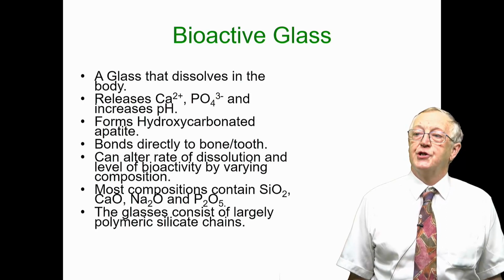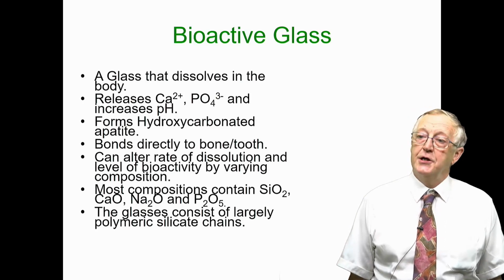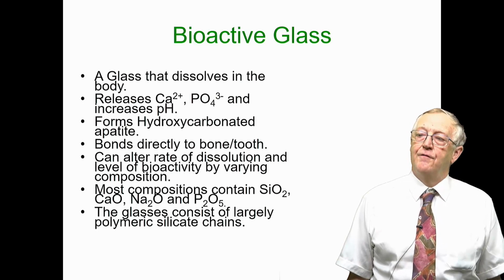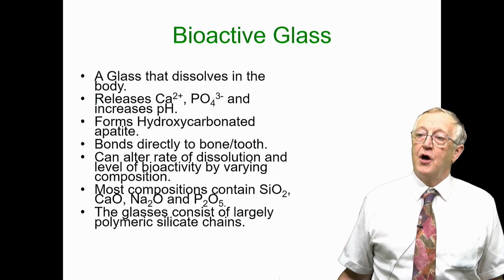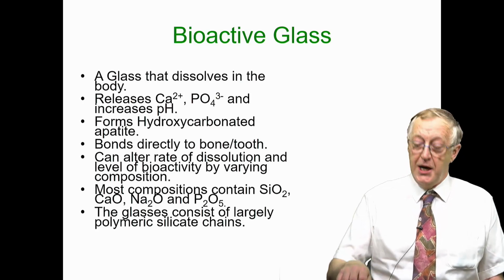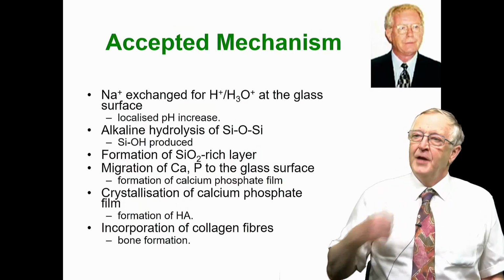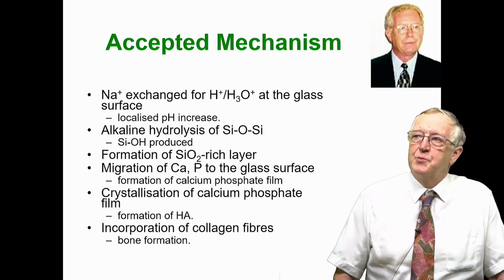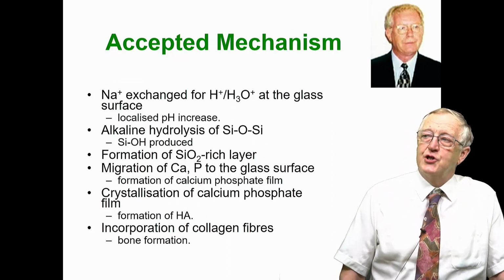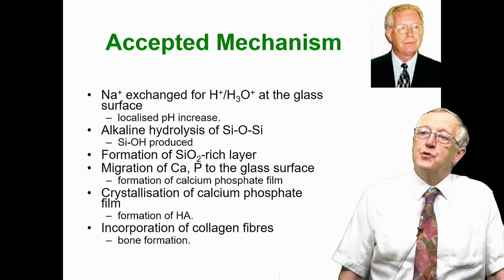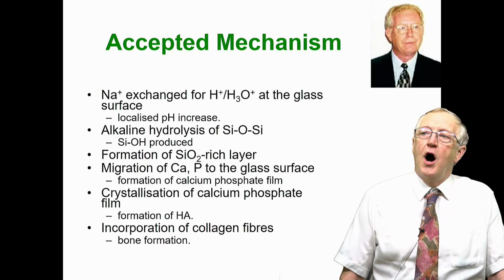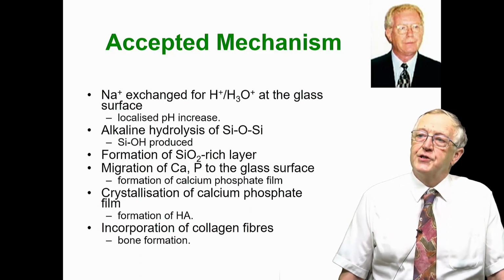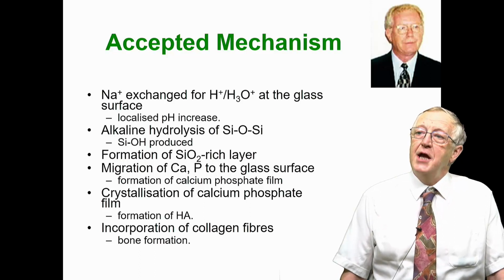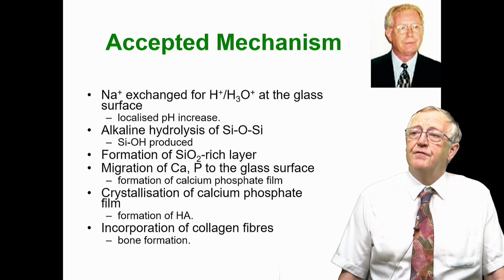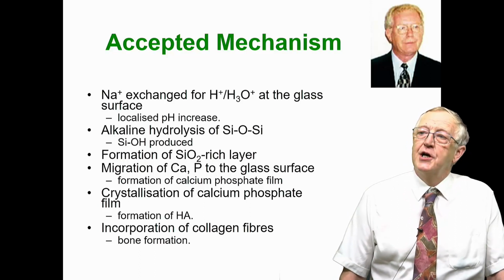And most compositions contain silica, calcium oxide, soda, and phosphate or P2O5. And the glasses consist largely of polymeric silicate chains. The accepted mechanism proposed by the inventor of bioglass, Larry Hench, shown in the top right there, is as follows. Sodium ions are exchanged for hydrogen ions at the glass surface. This exchange results in a localized pH increase, and this is particularly attractive for dental applications because caries and tooth decay occurs under acid conditions.